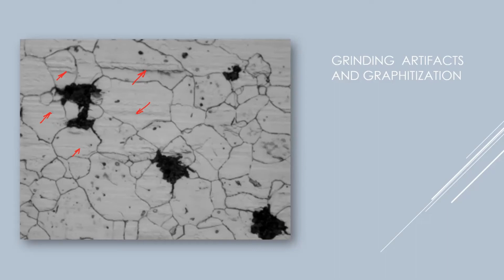Those things that look like, I don't know, squash bugs here, those black ones, are graphite nodules. This has been at high temperature, and so what's happened is all that iron carbide has converted into graphite. And those areas where I pointed the arrows, that's mechanical damage. That's another artifact. What's happened here is that I just didn't grind long enough to remove the mechanical damage. I still gave it to the client because really all he wanted to know was, do I have graphitization? And you can see how those little bands go from one grain boundary to the other.